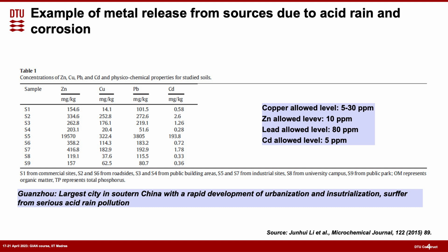And this one is from a public park, for example, and you can see that it is a little bit lower there. There are a few other things, like organic matter, which is not relevant for us, so I removed that. So you can clearly see a pattern here, depending on the type of place and exposure, where you expect higher pollution for the industrial sites, you get a much higher degree of this release compared to other regions.